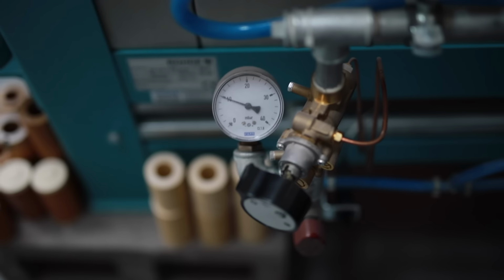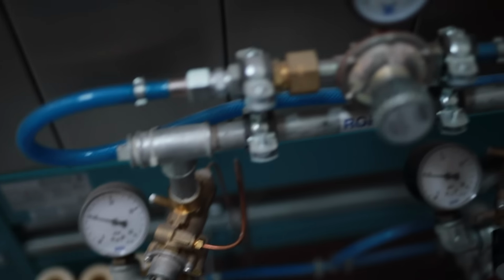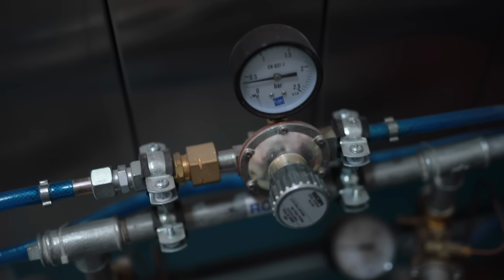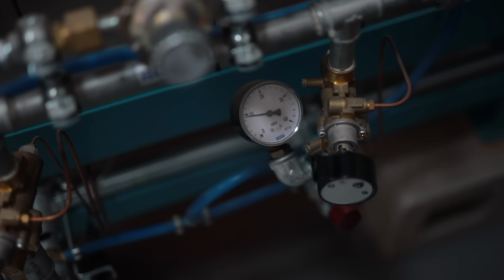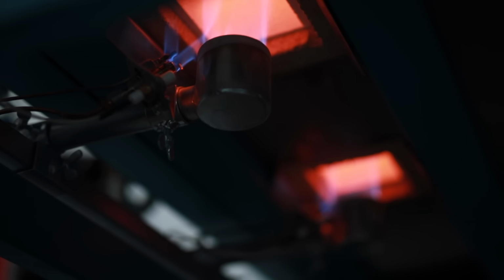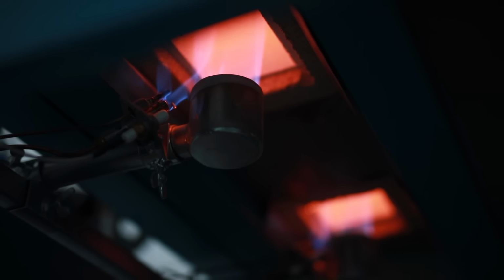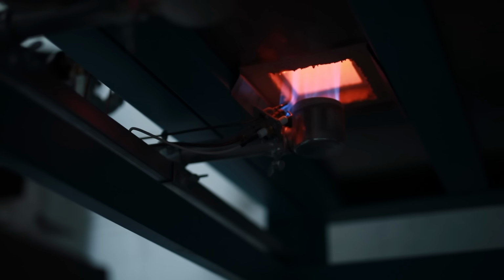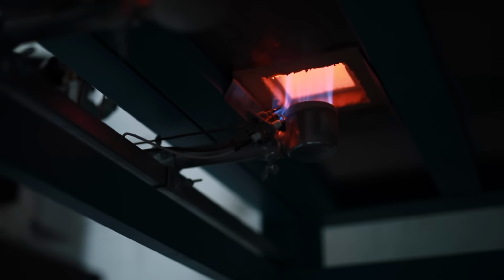And that's it. Reduction should be set at that point, and you can see it successfully when flames start to lick out the flues at the back here. There's also a very specific, almost sulphuric smell that emanates from the kiln very briefly. Both are good indicators of reduction. I should note, a reduction atmosphere is needed as it chemically alters the iron that my clay and glazes contain and allows them to fire to the correct colour.